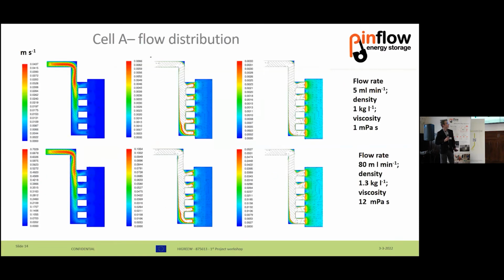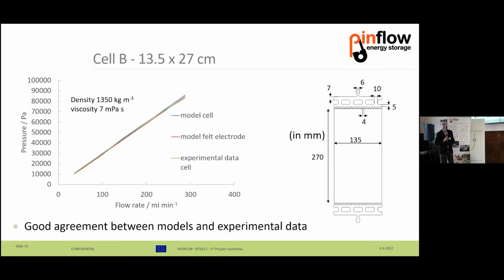What is positive if we get a very high pressure drop in the felt electrode is that we get very homogeneous flow distribution. You can see that for both very high flow rate and very low flow rate, the distribution of the flow is very, very good. In the felt, there is only some small inhomogeneity at the inlet, but after that it's absolutely homogeneous. So this is good, the flow distribution is also good.